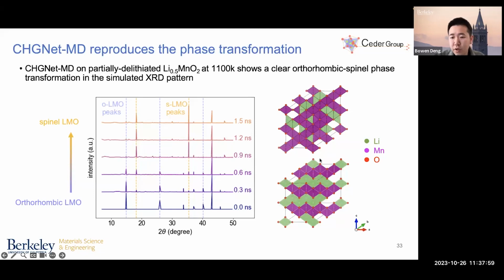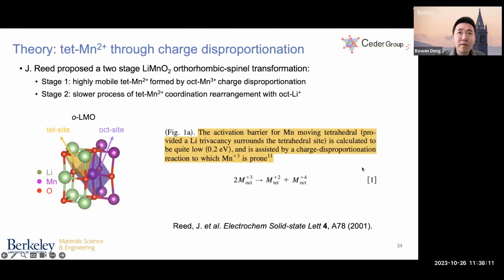And the initial structure and the final structure are plotted on the right, so they can show the migration of both lithium ions and manganese ions that accommodates this phase transformation. But the story of this lithium manganese oxide phase transformation is actually far more complicated and far more interesting than just the structural transformation. To convince you, let's look at how this mechanism was proposed in the early 2000s.